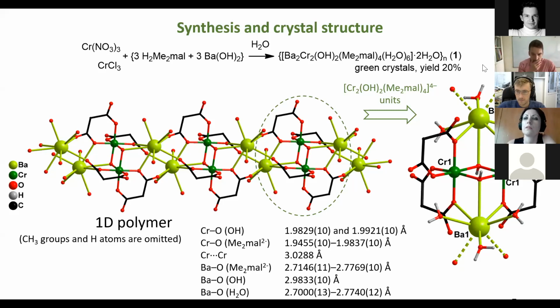The reaction of chromium nitrate with barium dimethyl malonate taken in a ratio of 1 to 3 in an aqueous solution gave the crystals of a one-dimensional polymeric compound composed of binuclear anionic units, in which two chromium atoms are linked by two bridging hydroxyl groups. Each chromium atom is coordinated by two dimethyl malonate anions in a chelating mode.